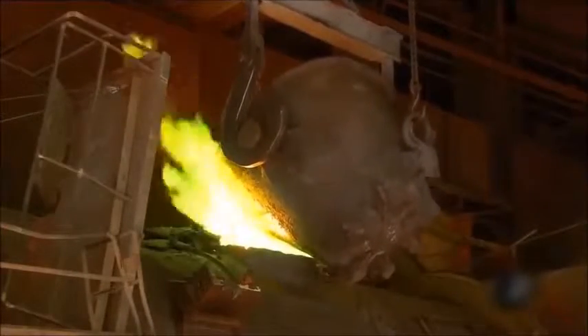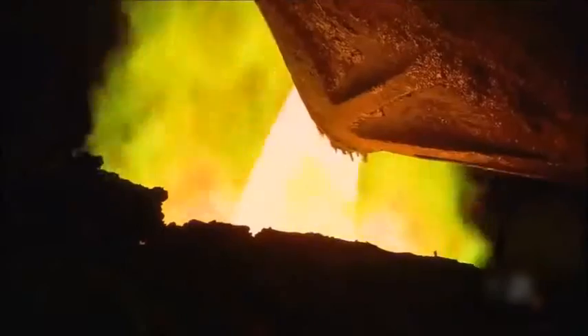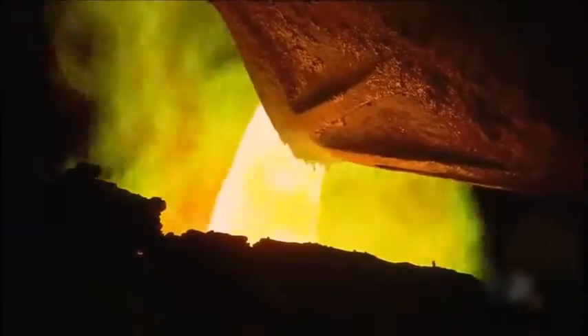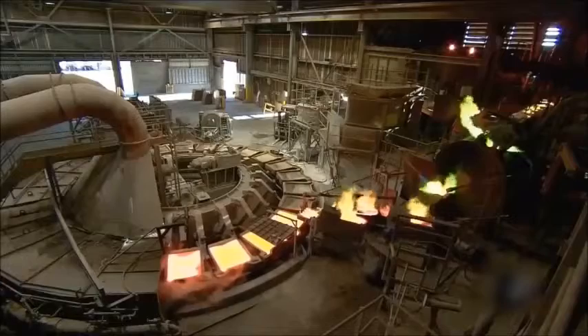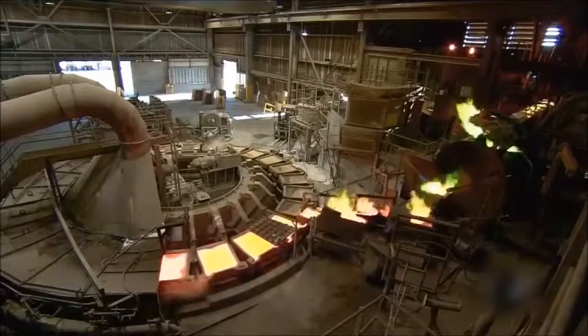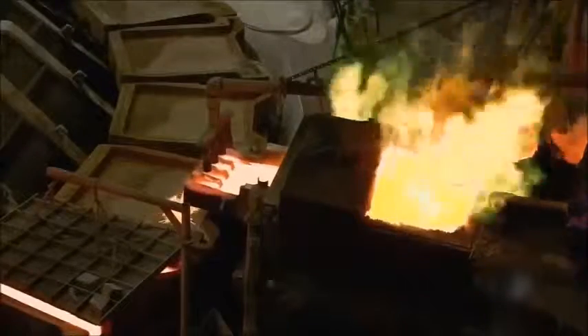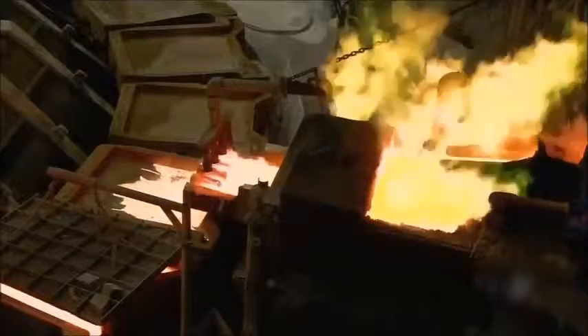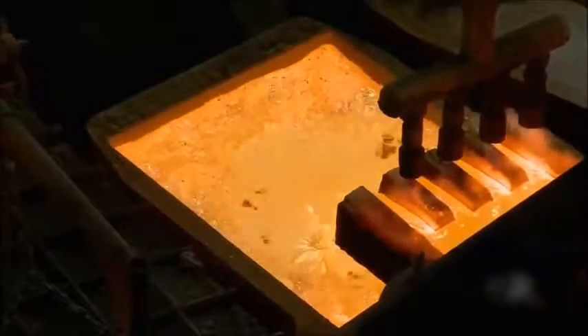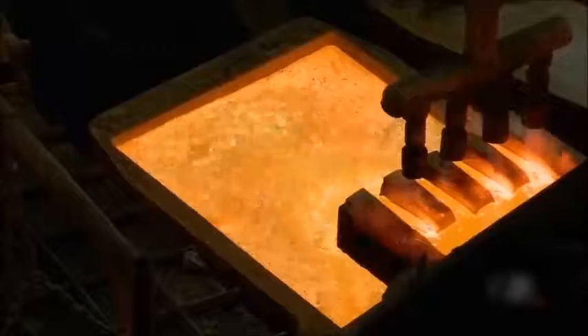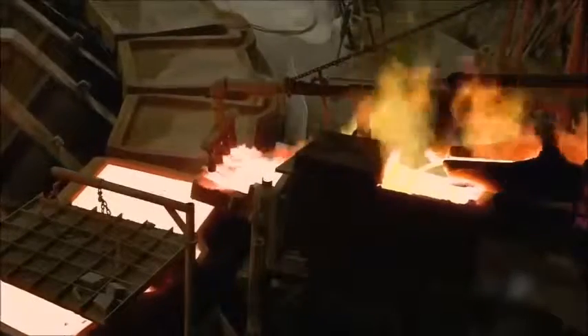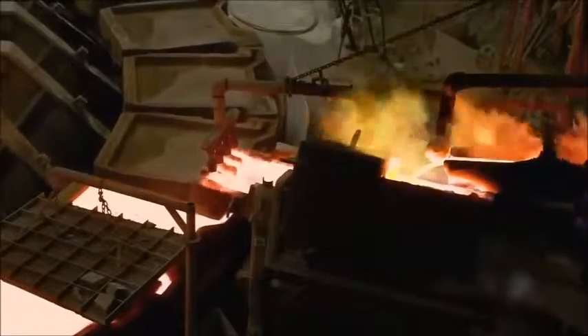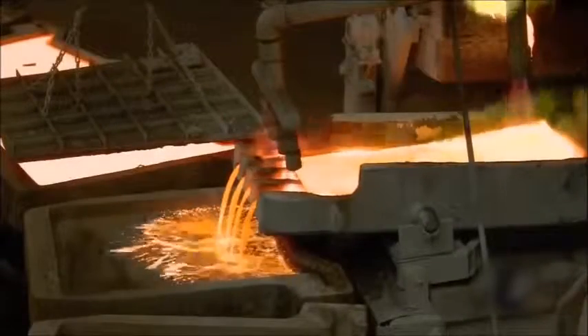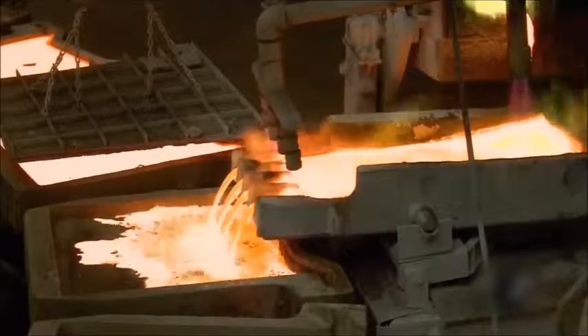Inside this furnace, the purity level increases from 98% to 99.4%. The molten copper flows out of the furnace and into rotating molds. The molds shape the copper into big rectangular slabs called anodes. The slabs will serve as positively charged electrodes in the electro-refining process that's still to come. That process will take the purity level up one last notch.